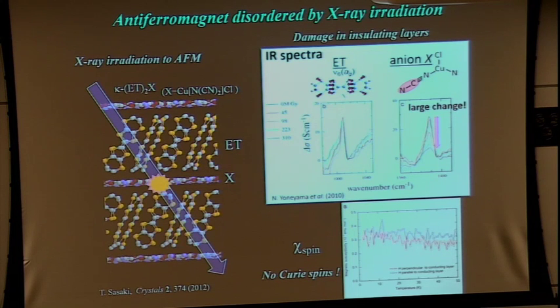And this is the optical measurement, namely the infrared spectra of some stretching modes in the insulating layers and the ET molecules. As the time of the irradiation is increased, the ET molecule does not show any change in the intensity of the absorption of the stretching mode. However, this CN stretching mode, this is the anion, the insulating layer, the peak is decreased. This means some leakage or destruction of this chemical bonding. So by X-ray irradiation, some disorder occurs in the insulating layers.